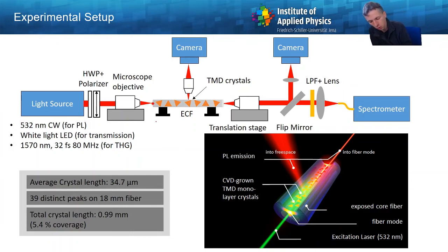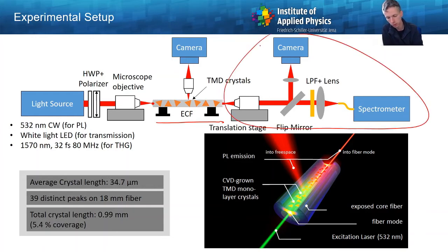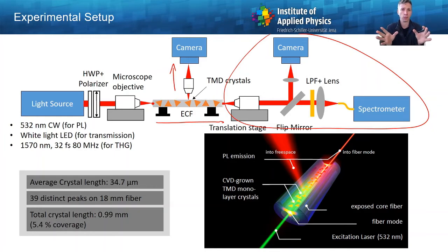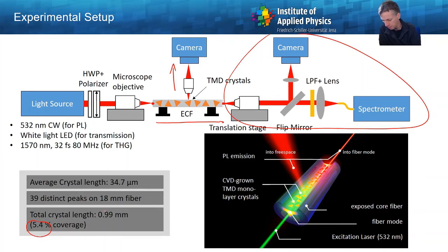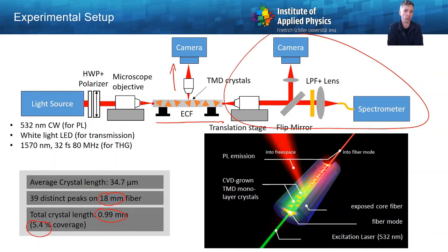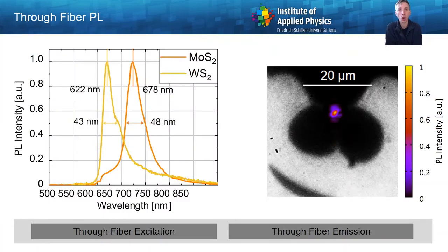Now we're ready to do in-fiber experiments. We take a light source, focus it into the fiber core, propagate light down the optical fiber, and observe what comes out the other side using cameras or spectrometers, or observe light emitted sideways using a camera. Sideways emission is used to determine the area coverage of our MoS₂ on the optical fibers. For this specific fiber, we found roughly five percent area coverage and a total amount of crystals on an 18 millimeter long fiber of roughly one millimeter. Usually you have an interaction length of one nanometer with transition metal dichalcogenides; now we have an interaction length of one millimeter — that's six orders of magnitude increase.